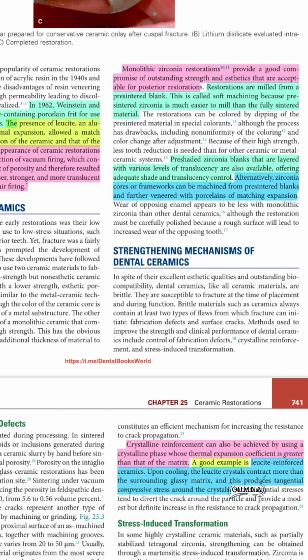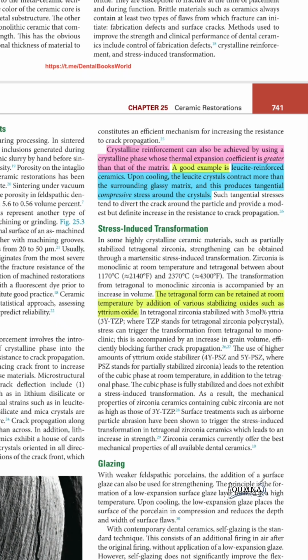We must compensate for the 25% of shrinkage that happens during the manufacturing, so we must increase the size of the restoration. Also, to increase the aesthetic of the zirconia, we can add the feldspathic layer of porcelain, which is highly aesthetic. However, it may be subjected to cracks or breakage that can be fixed by replacing the whole crown or doing a repair using composite resins, or just polishing the broken side.